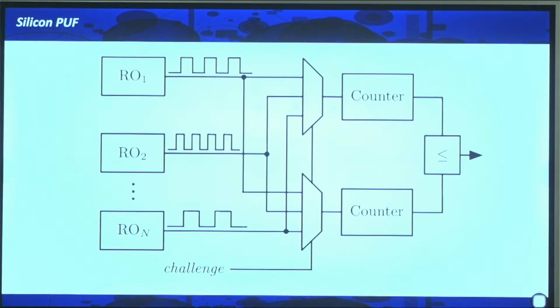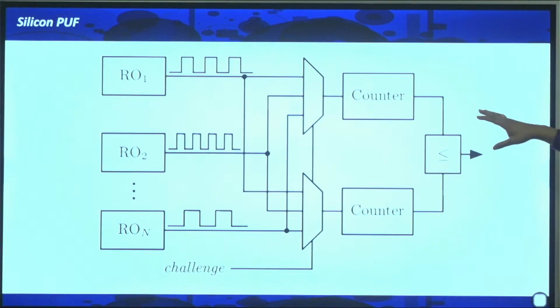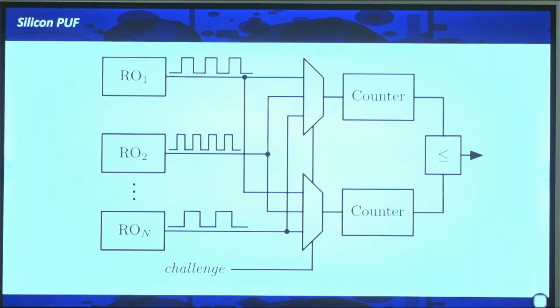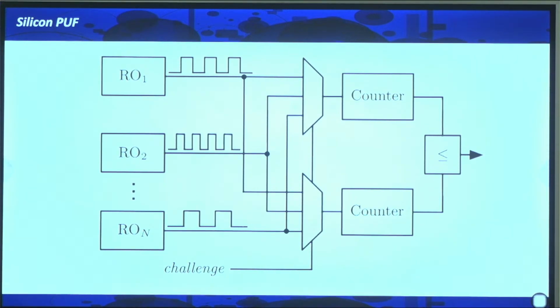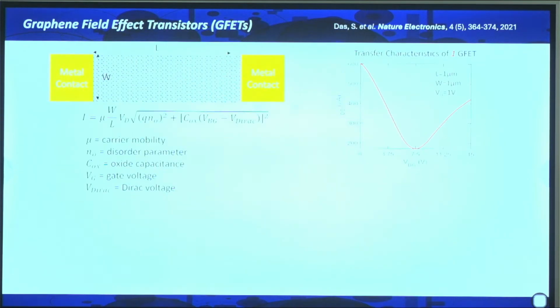What you do is you create these different ring oscillators. These are different clocks that are available within the chip, and each silicon device, right, might be slightly different. Although they are exactly the same, that's what the manufacturing process has ensured, but there could be some device to device variation. And that may lead to a little bit of change in the clock frequency. Okay? And then if you create a structure like this, then you can harness that. I'm not going to go into the detail of this because I'm going to give you a much simpler example using 2D materials. Okay? So I'm going to go directly to that, where I'm going to use graphene.